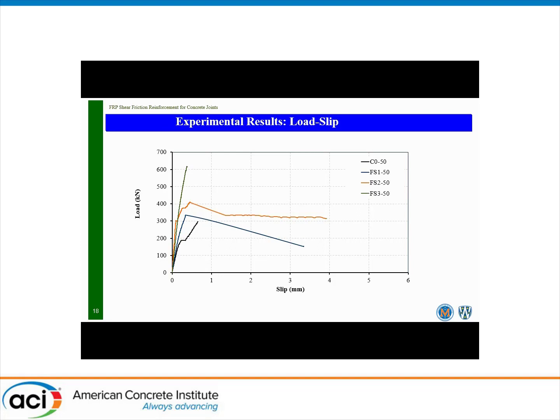FS3 with 3 FRP stirrups - this is when we were testing it vertically. We hit the maximum capacity we could obtain, around 620, and we couldn't initiate a failure for this specimen.